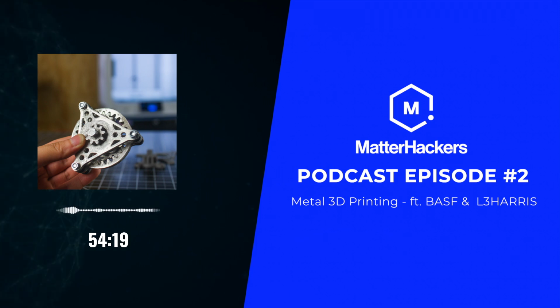The main thing, the adhesion can be an issue, but actually with BASF materials and the Dimafix, what is more likely to happen is that you have too good of adhesion, not bad adhesion. The issue with that is that removing your parts from the bed becomes the tricky thing, not getting them to stick for the first layer. So there are tips and tricks for that, or ways to avoid that. But essentially, the larger your part, the more difficult it'll be to remove. And so you may need to employ one or more of those techniques for removal.